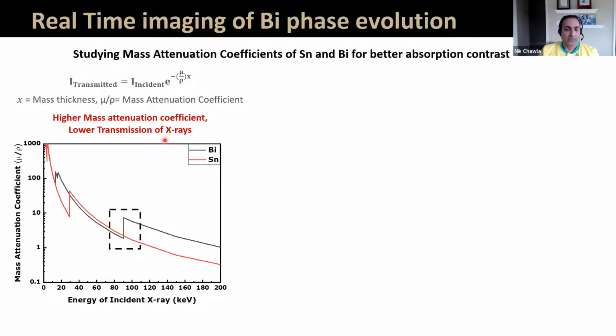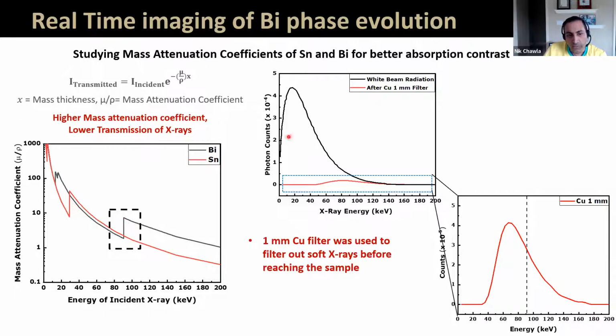Okay, so coming back to the energy range, if you look at the physics of this, this is the equation for the transmitted beam as a function of the incident beam, but we need to look at the mass attenuation coefficient. Okay, so the higher the mass attenuation coefficient, the lower the transmission of X-rays, of course. But because we have tin and bismuth, we're trying to shoot for the energy range where we have the largest difference in mass attenuation coefficient. The largest difference will give you the largest amount of contrast. So we have a white beam, and we want to zero in on this region, or at least get a peak in energy between 80 and 100 keV.